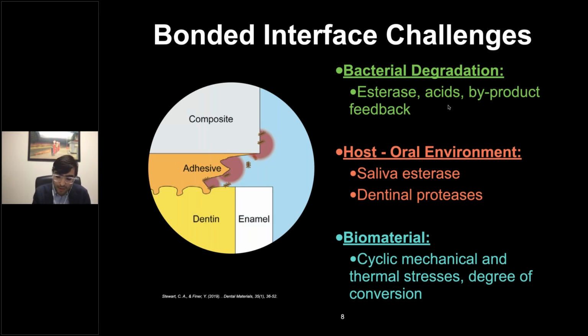The other two enemies that these interfaces have are the saliva, again more esterases produced and found in saliva that cause degradation of these materials. Also there are enzymatic processes, the MMPs activated in dentin, that are degraded when exposed to acids or clinical procedures. And more than that, mastication forces, the cyclic repetitive forces we experience when we chew and masticate food, also degrade the conditions, as well as thermal changes, because we drink hot and cold foods.